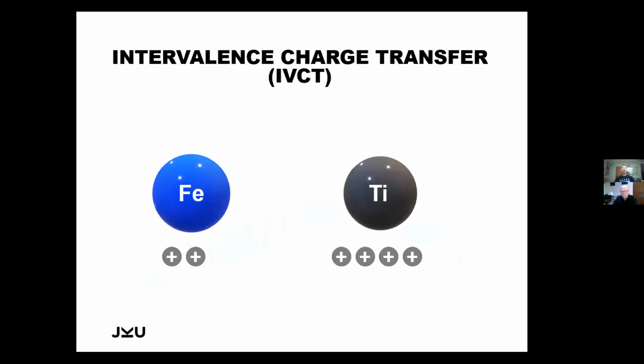The next mechanism we're talking about is the so-called intervalence charge transfer, or IVCT for short. Intervalence charge transfer means that we now have a transfer of one electron from one atom to another atom. This can be either between the same type of atoms, like from an iron to an iron, but the most prominent one here is from an iron to titanium. In the general state, we have iron as a 2+ ion, and titanium as a 4+ ion. Now, if we have light of the proper energy, then one of the electrons from the iron is transferred onto the titanium, and both end up at 3+. So we're electrically neutral. We just shifted one electron from here to here.